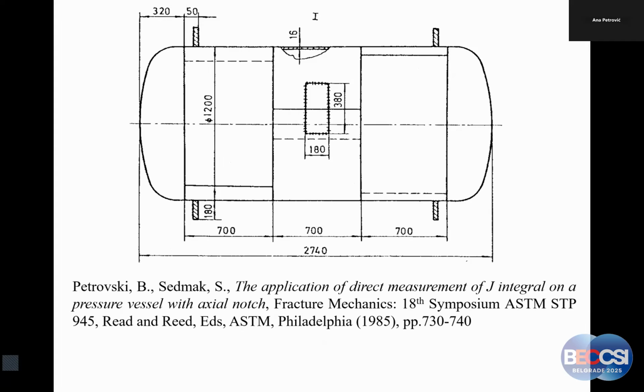And now I come to the most interesting part of this story. In ex-Yugoslavia, on 2 occasions, very interesting experiments were made on pressure vessels. You can see here that there is a part of this pressure vessel which was cut out and then welded back. In the meantime, complete instrumentation for measuring strains was installed. So that was a unique experiment that enabled us to measure J integral on a pressure vessel. Without this cutout piece, you cannot approach the inner side, and we need both outer and inner side.